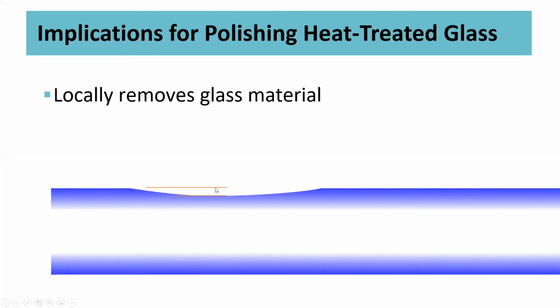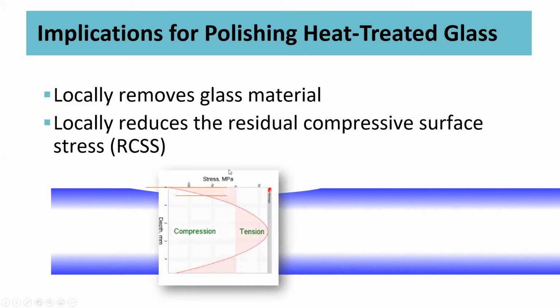Now, in addition to removing the glass material itself, correspondingly, we're going to locally reduce that RCSS as well, because we know that it was a function of its depth through the glass. And there are a few issues that come to mind when we think about this. That stress had to go somewhere to balance our internal stresses. So we need to be careful about what we assume. Is that going to be that change?